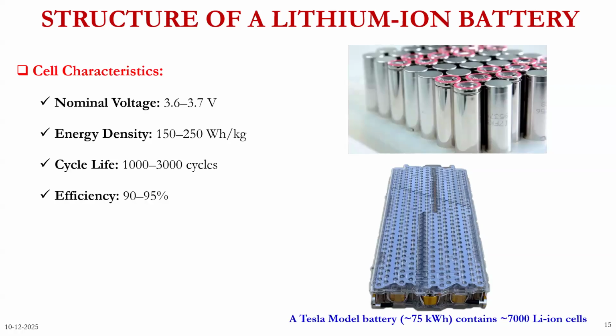Again, when you start using your battery, after 20% you should not use it further. So this should be your charge discharge cycle. Then the performance of the lithium ion battery will be excellent. A cycle means going from complete discharge to 100% or maximum SOC, and from there again to the minimum SOC. If you use this range, your battery will work very well, and it will last for a very long period. So these are the characteristics of your cell.